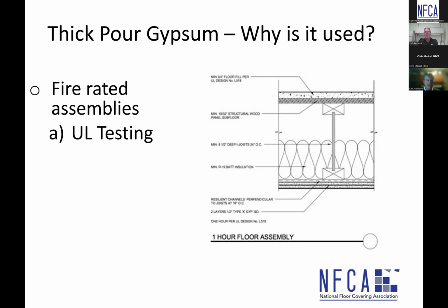So typical self-leveling underlayments are poured maybe an 1/8 inch to a 1/4 inch to create a smooth floor. The thick pour gypsum is a minimum of 3/4 of an inch over the whole floor. The reality is they're probably poured anywhere from 3/4 up to 1.5 inches, and sometimes deeper, all depending on the flatness of the floor and the substrate that they're going over. But when I say thick pour, it's minimum 3/4 of an inch. These types of gypsum materials, quite frankly, can't perform at a 1/2 inch or a 1/4 inch or an 1/8 inch or a feathered edge. It's a minimum 3/4 over the whole floor.